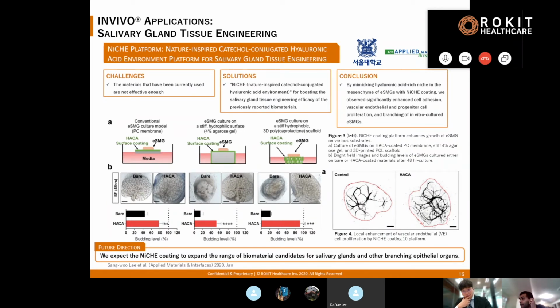This also shows that there is enhanced vascular endothelial cell growth, as you can see in the branching here, using the NICE coating. This is a quantification of the budding levels to quantify the amount of budding in the coated versions. So the group expects that the coating will expand the range of biomaterial candidates for researchers doing salivary gland and other epithelial organ tissue engineering.